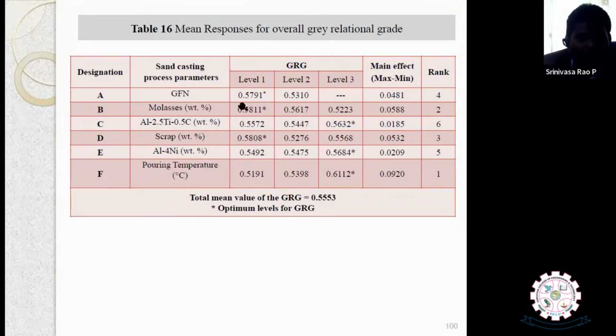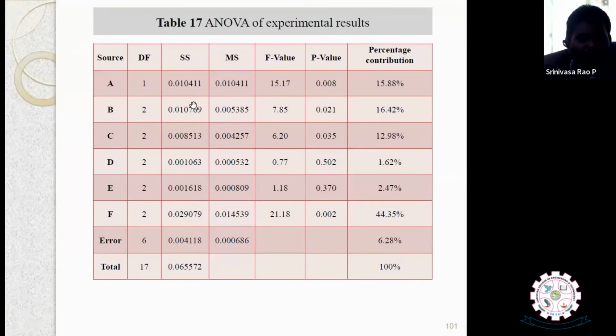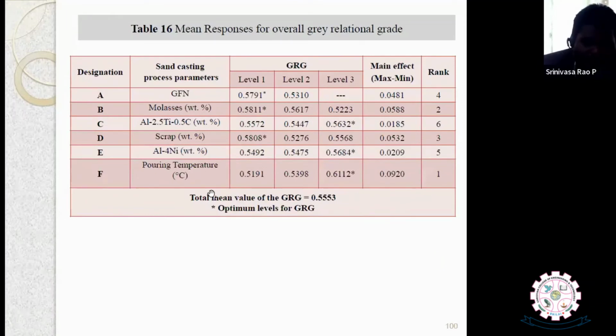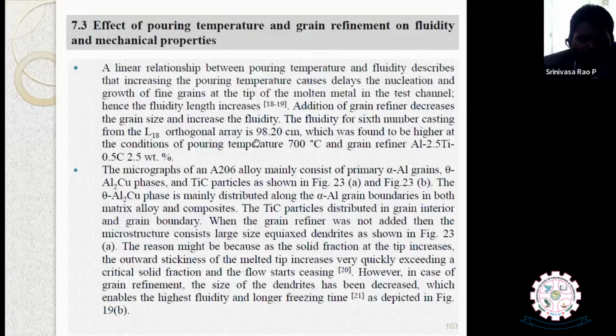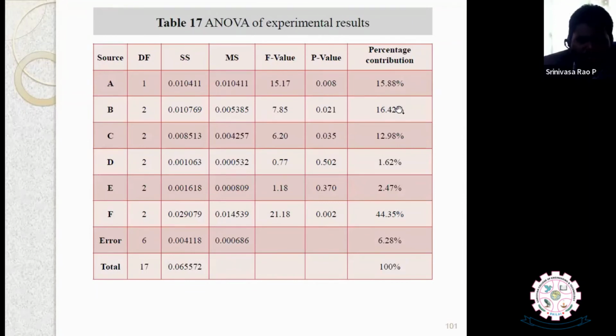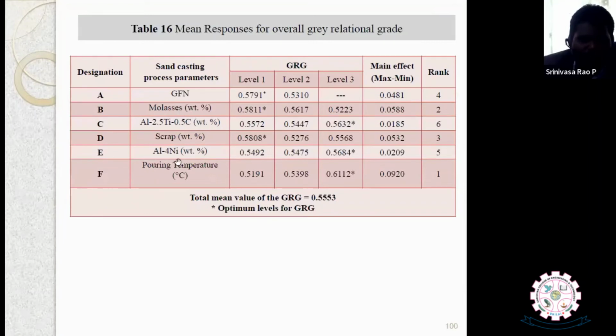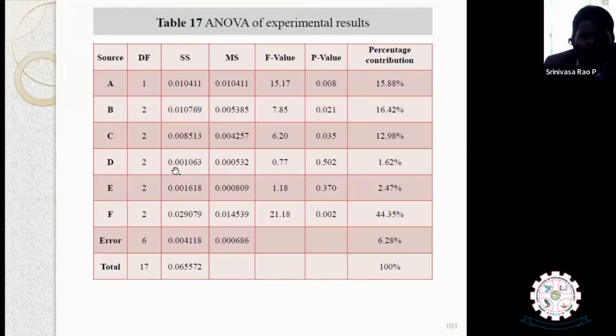So grain fineness number at level one, molasses at level one, the grain refiner at level three, scrap at level one, aluminum nickel at level three, and also pouring temperature. After that we carried out the ANOVA of the experimental results, and this is the percentage of contribution. You see the maximum percentage of contribution is F. That is, the pouring temperature plays the main vital role in increasing the casting quality, considering all other parameters. After that the grain fineness number also makes a large contribution, and then B is the molasses. So grain fineness number, molasses, and pouring temperature play the main vital role in improving the quality of castings.